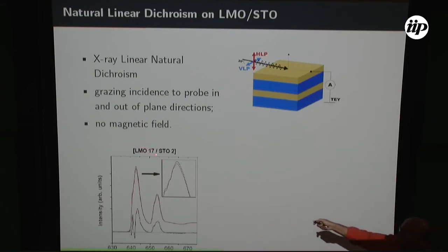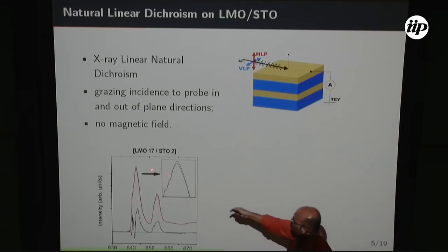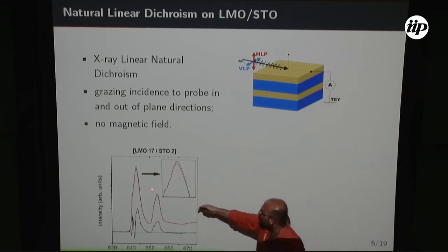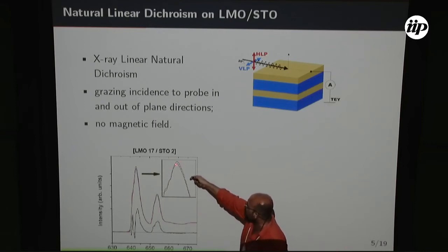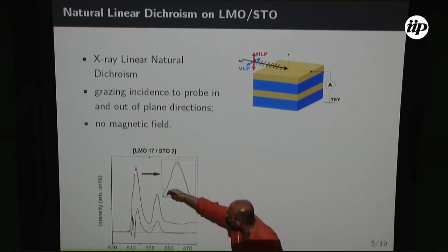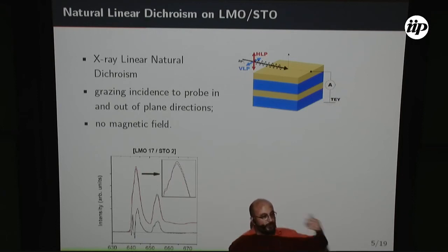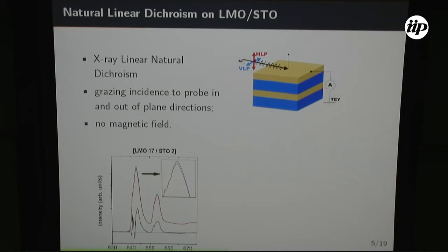So 17 unit cells. We measure one polarization, another polarization. If you notice here in the zoom, there's a very small difference there. What you have when you do X-ray absorption is that you promote electrons from the core levels to the empty levels. The direction that has more empty levels has more absorption. So in this case, this signal, without any interpretation, says you have more empty states for the blue, the vertical.